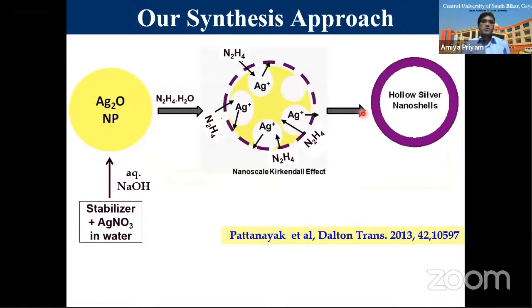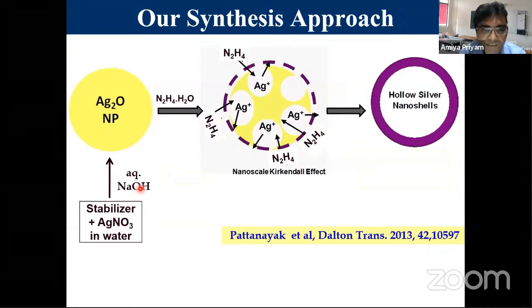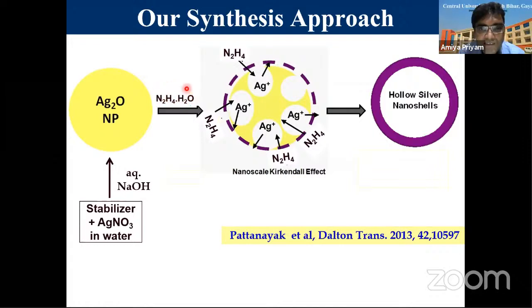So we designed our own methods, and this is what I remember from the first talk. Dr. Shrikant also talked about the nanoscale Kirkendall effect while talking about hollow magnetic particles. So this is also a nanoscale Kirkendall effect, which we have modified, and it is a different way. In this, we make a silver oxide nanoparticle first, using typical reagents like silver nitrate and NaOH, that is sodium hydroxide, and then use a mild reducing agent. This is hydrazine hydrate, which is a mild reducing agent.